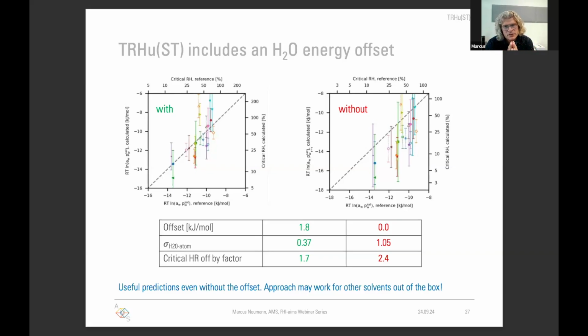And that is because there is a small error on the free energy difference between water in the gas phase and water in the solid state. And the practical way to solve this easily is that you fit in a free energy offset for water. And once you have that, then you get the plot to the left. Still, this method, we expect it to work for all solvent systems. And I have to show you two numbers there. So please, in the table, look only at the bottom numbers.